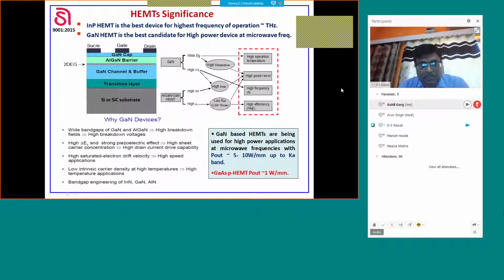So this I'll not be discussing in detail, just to tell you that the best frequency performance is still possible using indium phosphide HEMTs, and the cutoff frequencies or the maximum frequency reported, Fmax, is of the order of terahertz. Whereas if we need high power at high frequency, then the gallium nitride HEMT is the best candidate.